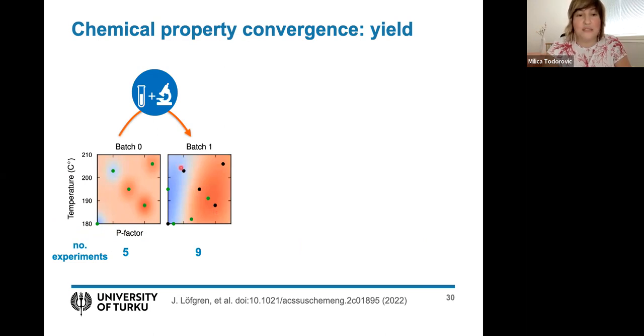Now you can see the new experiments, the old experiments are now in black, and the new data points that were predicted for the next experimental batch are added in green. So this is what the model looks like with nine data points, and you can see it's changing, and there is a region now of high yield and a low yield on both sides.